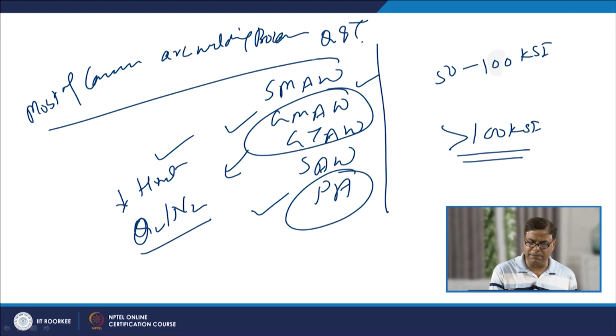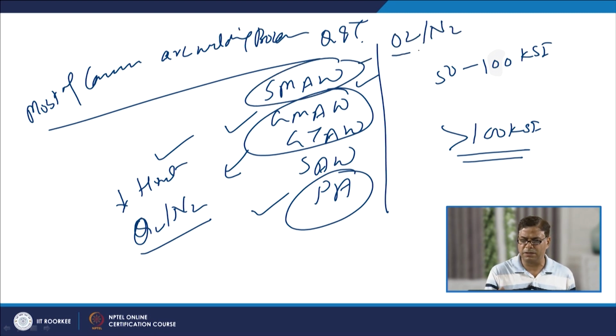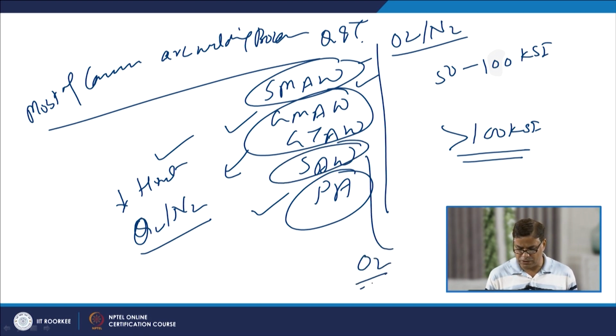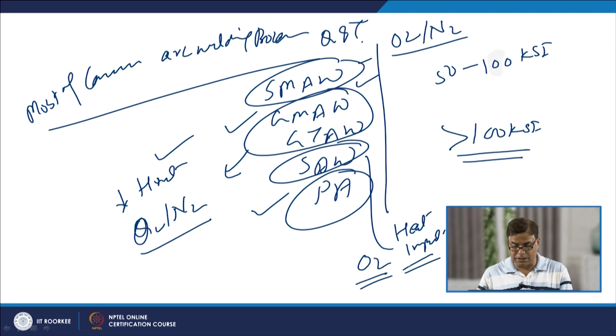While other processes like SMAW offer a higher concentration of oxygen and nitrogen in the weld metal, there are a lot of discontinuities in the weld metal. Since these Q&T steels are of high yield strength, they have less tolerance to discontinuities, and therefore they promote failure tendency. Likewise, SAW also offers a higher concentration of oxygen, and the heat input provided by SAW is also on the higher side. So, it results in weld discontinuities due to the oxygen present or the presence of flux inclusions, or the wider heat affected zone due to the higher heat input. So, we prefer to weld the high yield strength Q&T steels by GMAW, GTAW and PAW processes.